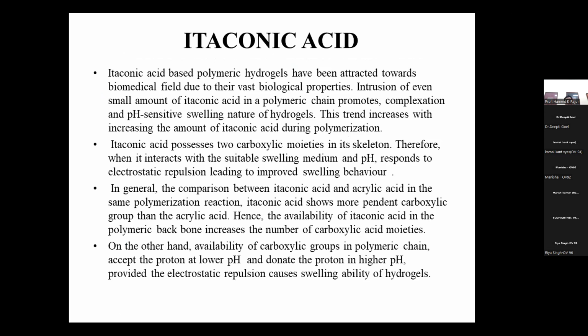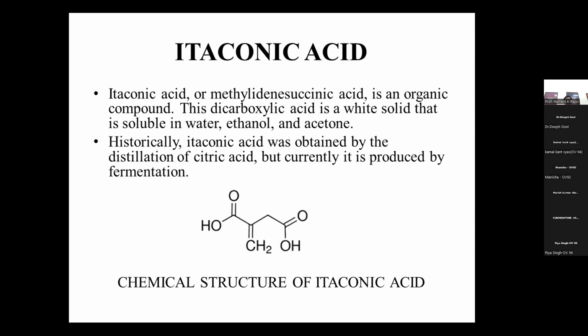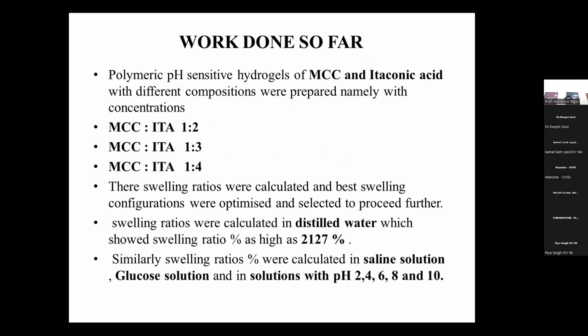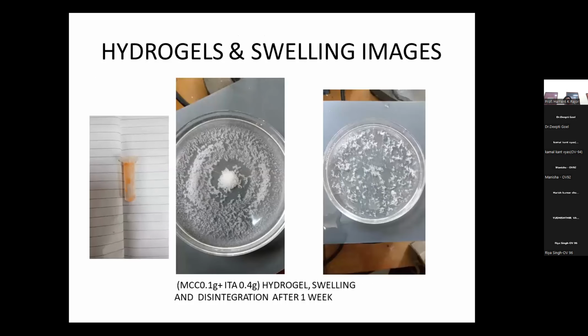Another ingredient is itaconic acid, and you see that it has two carboxylic moieties in its skeleton, which is important as it is responsible for its pH-sensitive nature. This itaconic acid is obtained from the distillation of citric acid and is produced by fermentation. In my work, I tried microcrystalline cellulose and itaconic acid in different proportions and compositions and came out with some of the best swelling ratios, which in distilled water was somewhere around 2,127%. These swelling ratios were calculated for other solutions as well.